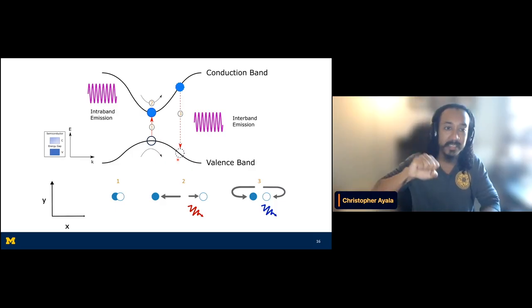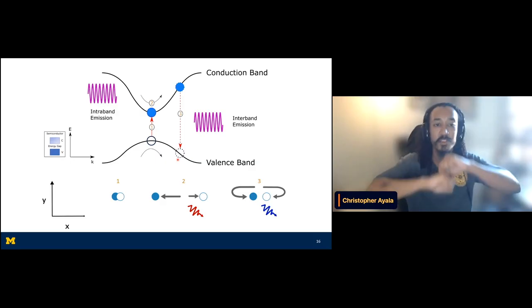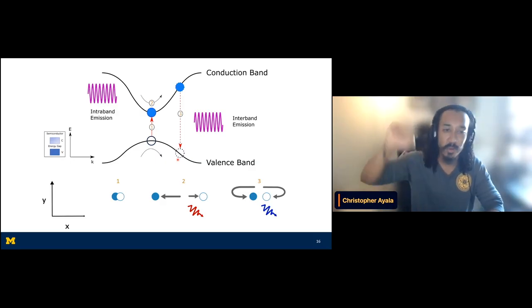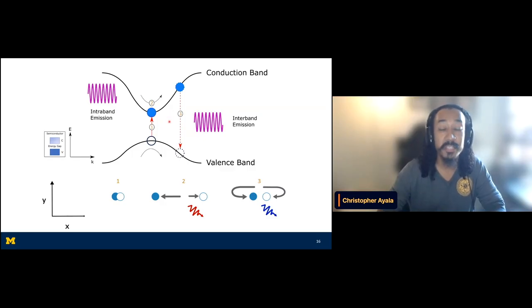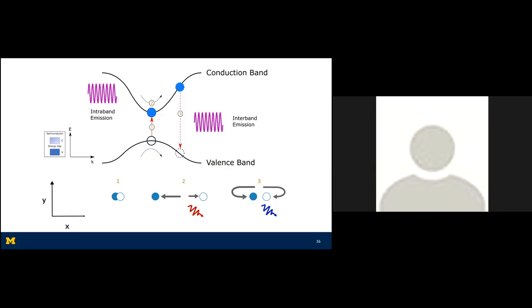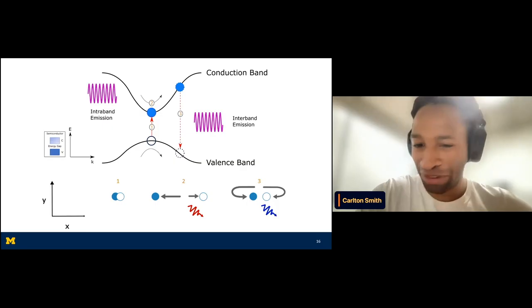Thank you. So what's happening is that this process is creating many electron hole pairs, and it's only in a few cases that they recombine together. Harmonics are always being generated, because in the solid case there are two forms of these harmonics. It's just that the recombination happens more infrequently than the intraband emission, but it doesn't have to be the exact same electron hole pair that was generated. As I stated earlier, this electron hole pair can form right here, it can form right next to it, and wherever it relaxes back down to its valence band, it produces that harmonic. That specific recombination type of harmonic. Okay, thank you. Thank you for the question.